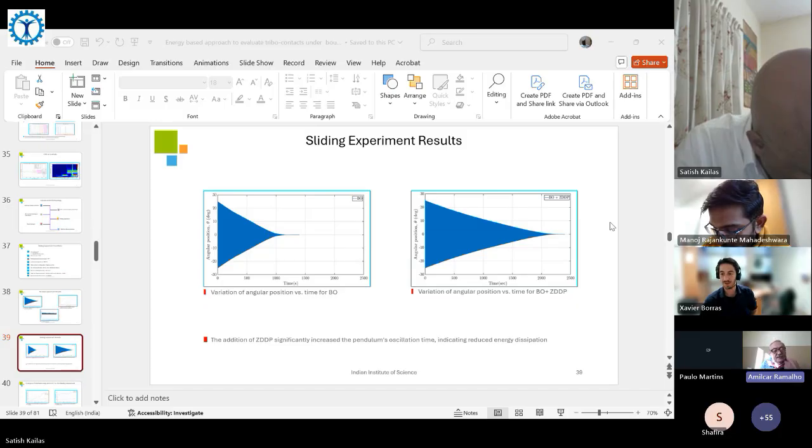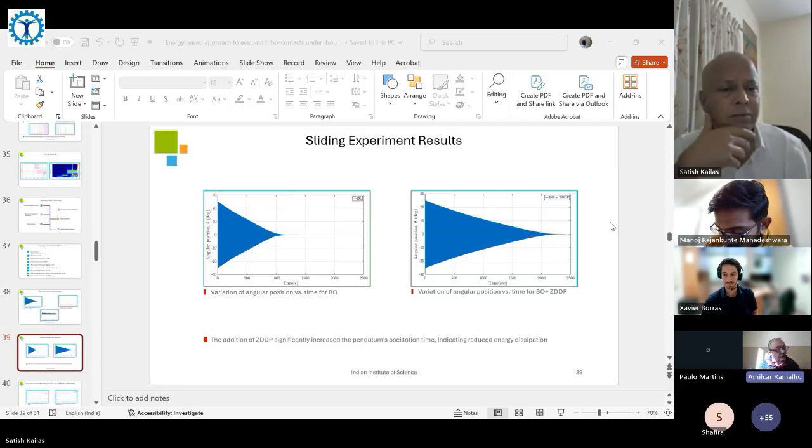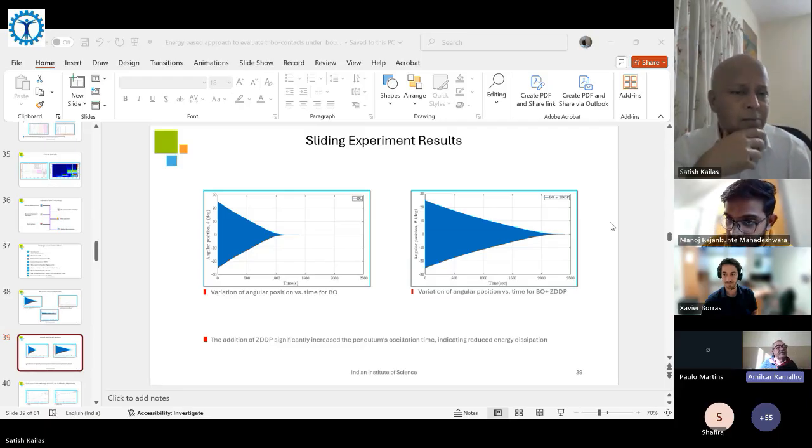And here I think the friction is much higher than I expected. Even in your work, using exactly the same fatty acid as you have shown in the first set of results, you have obtained a result of around 3 to 8 times 10 to the minus 2 for the friction coefficient.